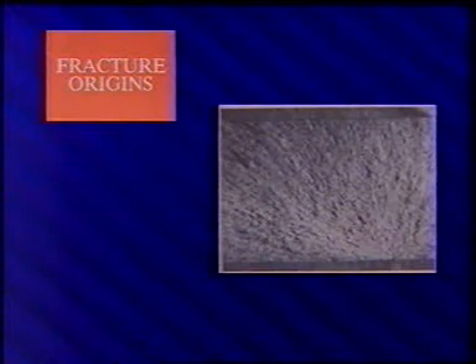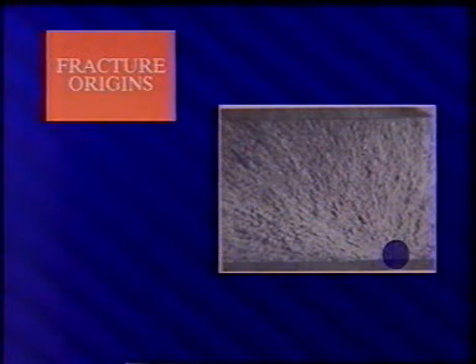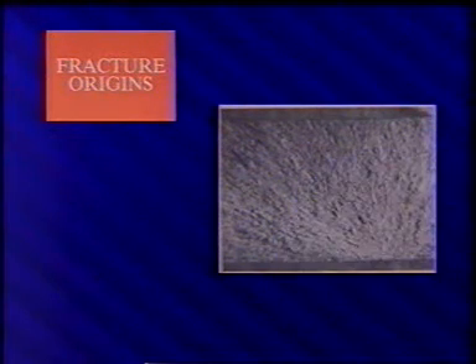When fracture occurs, it initiates at a notch. It makes no difference whether the notch is intentional or accidental. The radial marks on this fracture surface converge at a surface scratch that initiated the fracture.